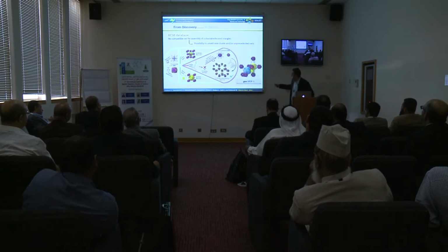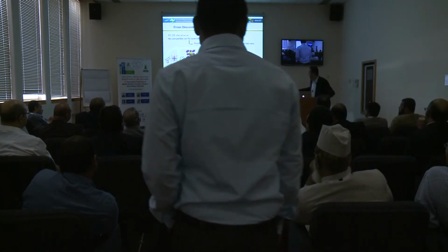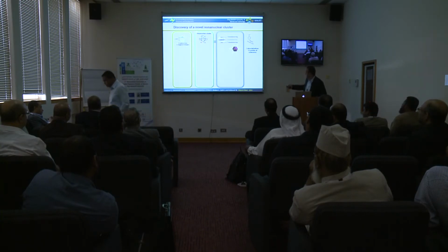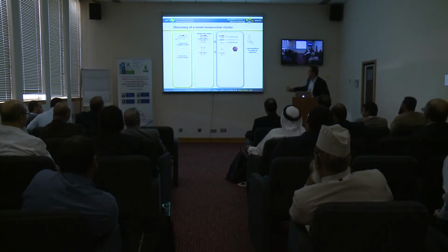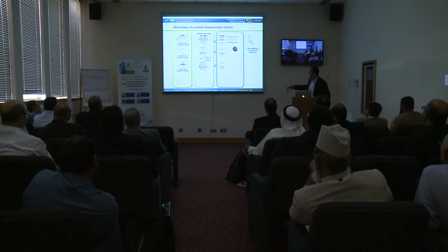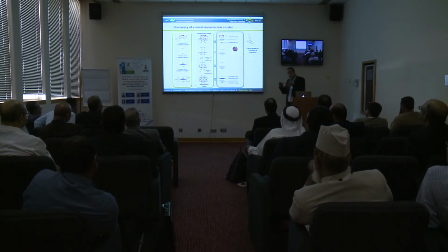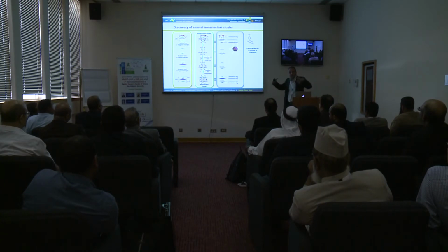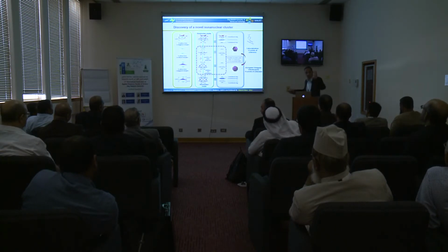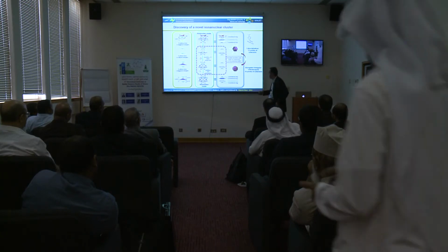So here we make a structure for the first time. What you have here is an evolution of the cluster. It goes from hexanuclear cluster to a nonanuclear cluster. This is the mechanism. Again, if you're interested, you can check the paper. So since this 12 connected is not compatible with triangle, 3 more metals came in to expand this carboxylate to be 18 connected now. And you make this kind of highly connected building block. Triangles with 18 connected, you make this new topology. And it's highly porous.